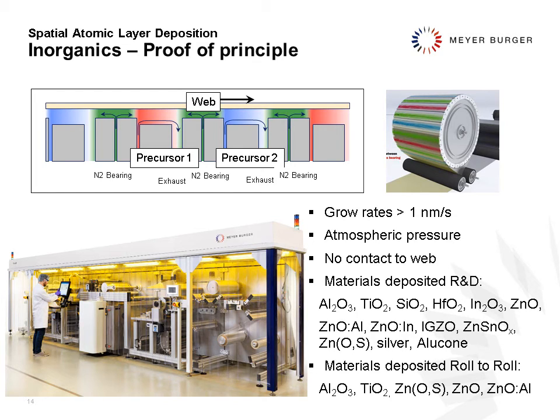And you can even go even further. You can put all of these chambers in a roll, in a drum, and therefore you can, by moving the drum or moving the web or moving both, achieve this spatial ALD. Now the growth rates are above 1 nanometer per second. It can be done at atmospheric pressure. There's no contact to the web.